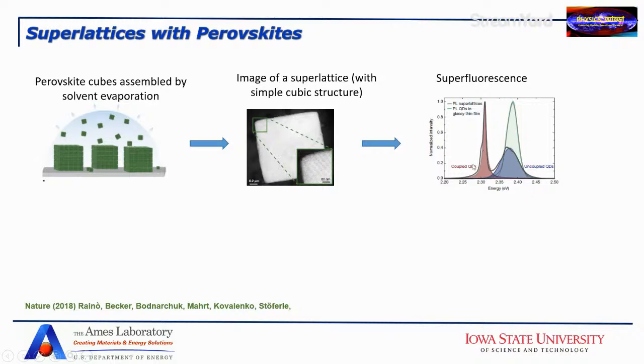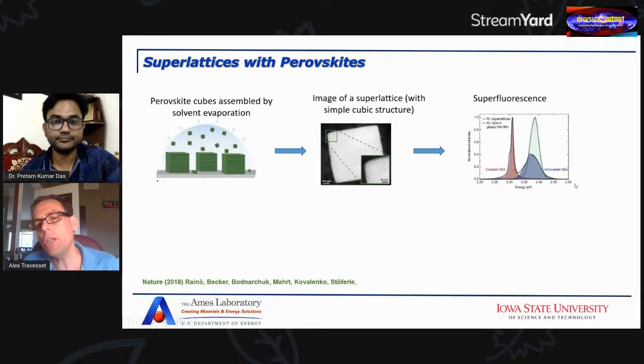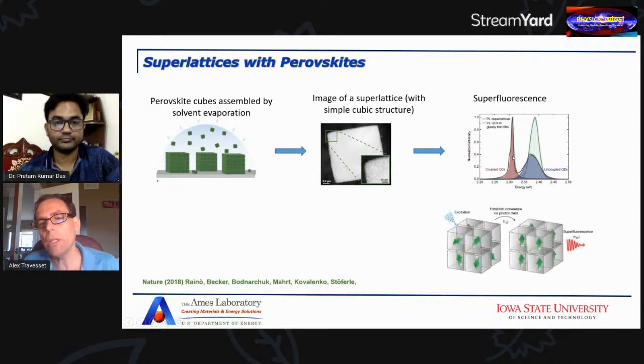So here you have the evidence. What you see is you shine electromagnetic radiation, and instead of re-emitting the electromagnetic radiation typically, as you heard, they do it as a single pulse. So basically what happens is that you excite the material, then all the different emission dipoles start aligning with each other, and when they are aligned, boom, they emit a huge burst, which has a lot of power, and it is very precise in terms of the wavelength. So this is actually an example that shows how the structure determines the function. This function here is this effect, which is called superfluorescence.